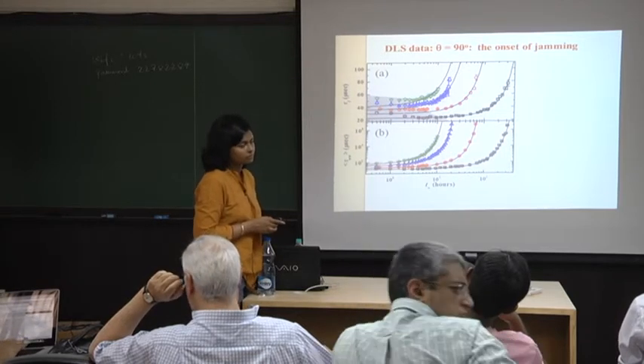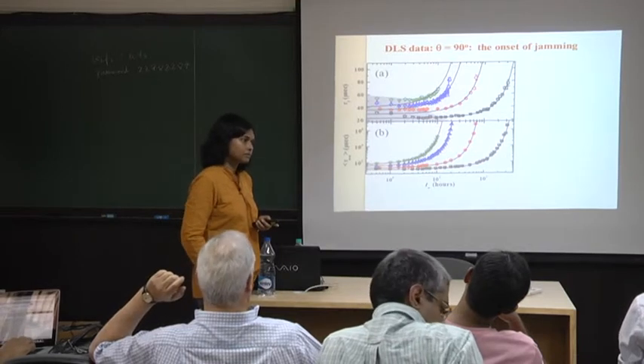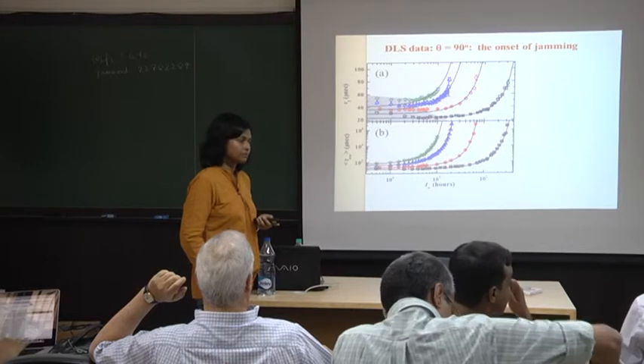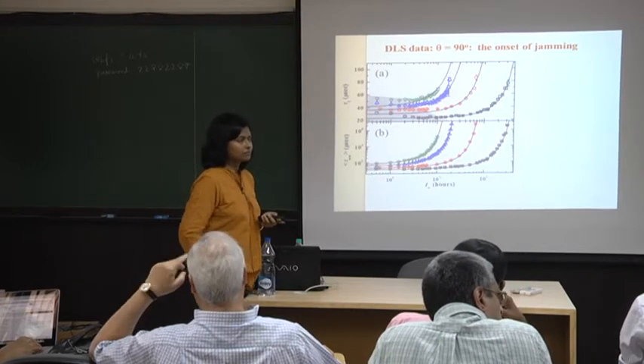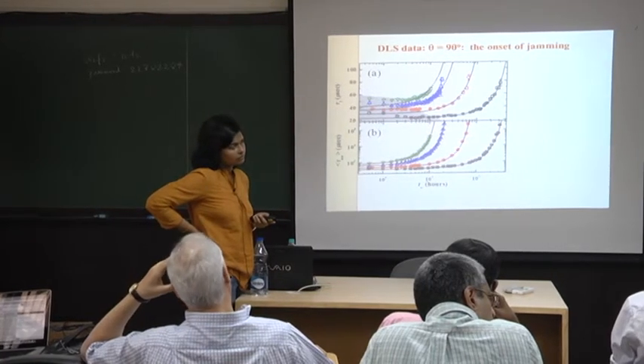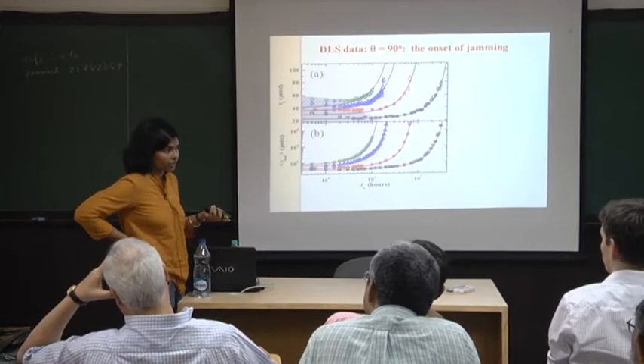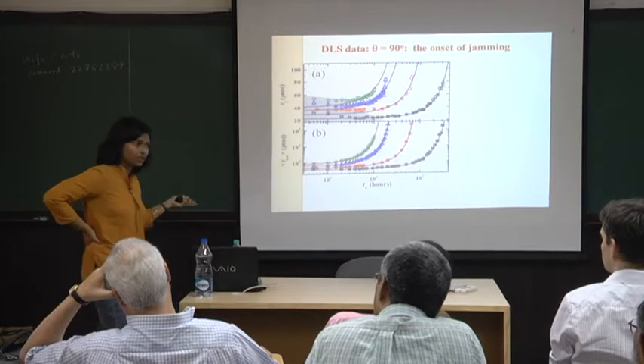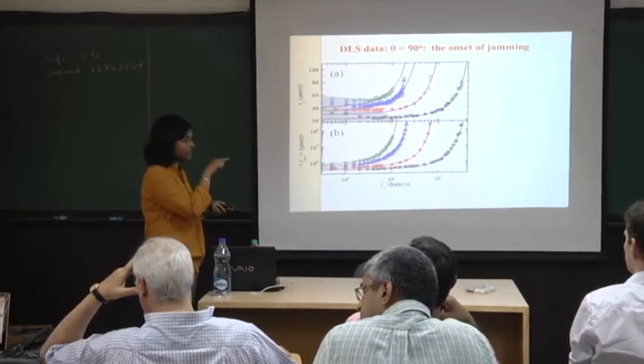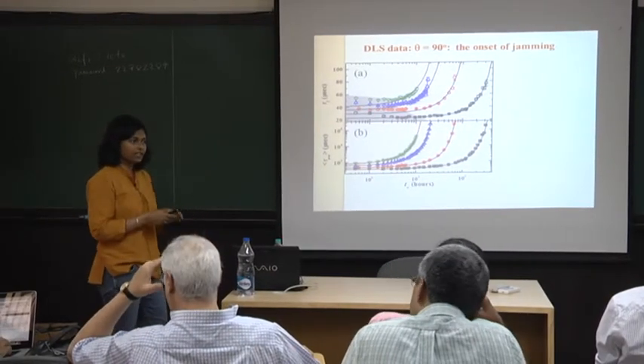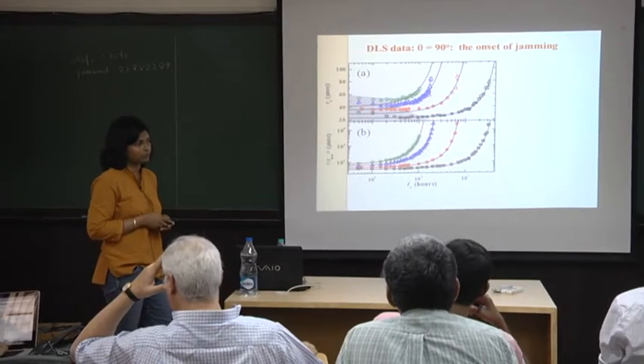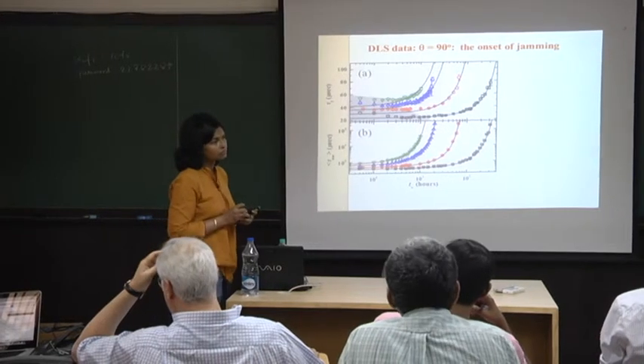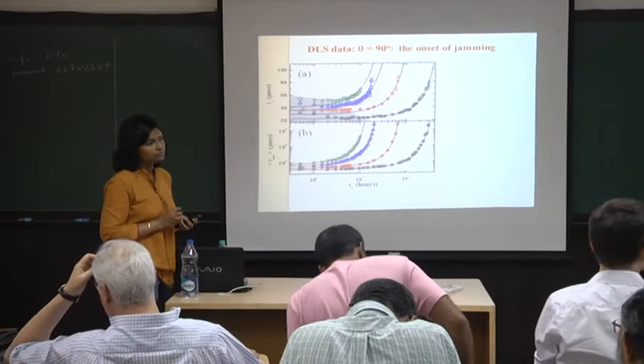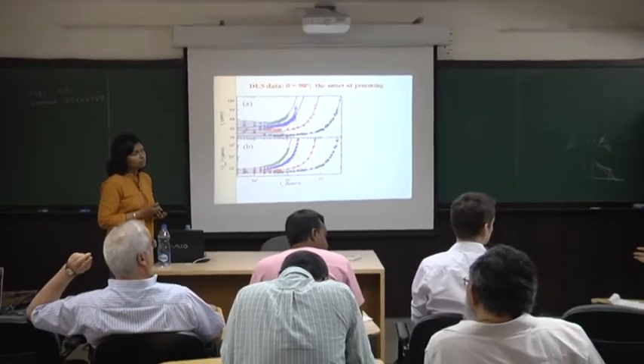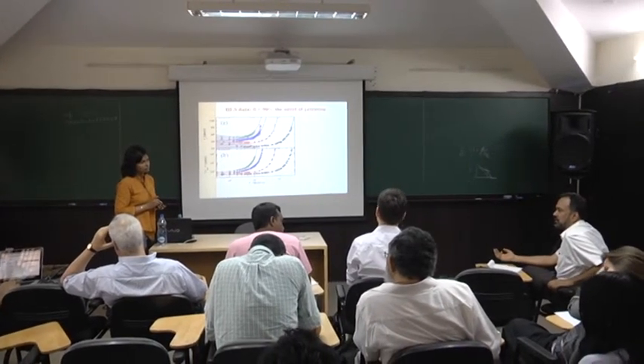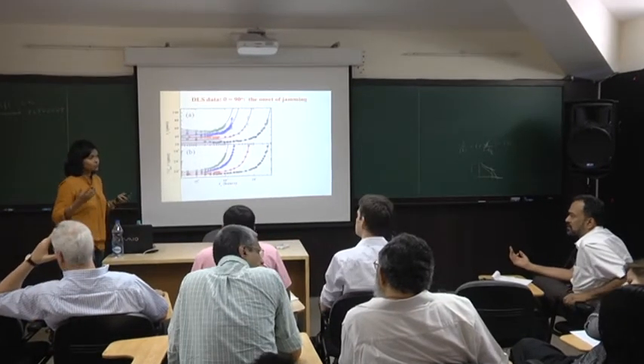Replacing the waiting time, it's not clear to me why you want to have a mapping to temperature, but normally that's not how people do it, right? You look at aging systems. No, they do it. For instance, people like Barbara Ruzicka were looking at it in a slightly different context. They were looking at the fragility parameter. They did a similar plot, and they showed that that parameter changes across the glass transition time. But if I do a simple thing where I quench the system to a low temperature, and the effective, whatever the physical temperature of the system is, aging, it wouldn't simply... I mean, it just works.